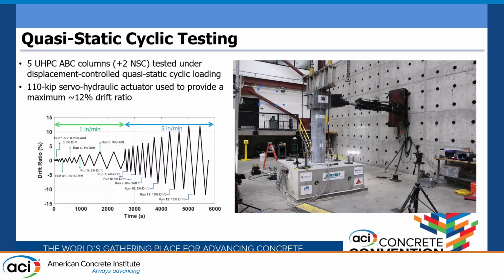But for the testing part, we did cyclic testing. Seven of them were under quasi-static cyclic testing. We used an actuator with 110 kips to reach drift ratios from 0.25 to 12%. Only one column reached around 12% drift ratio, which is funny. It's the recycled fiber in this case, which I will explain later, why we think it achieved much better. But pretty much this is the loading protocol that we have.